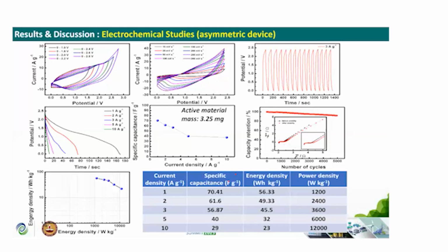Finally, we have fabricated the device using the nickel-cobalt sulfide as well as the iron oxide decorated nanoparticle as a positive and a negative electrode, using 10 molar sodium perchlorate as the electrolyte, because our aim is to increase the energy density due to the high concentration of sodium perchlorate. We can go to more than 2 volt working potential. In the first CV, we optimized the potential window of the fabricated device by tuning different potential windows, and observed 2.4 volt is optimum for the fabricated device. Hence, we have used this potential window for further detailed studies.